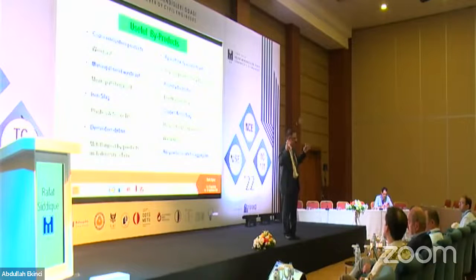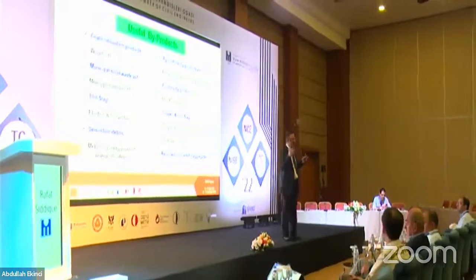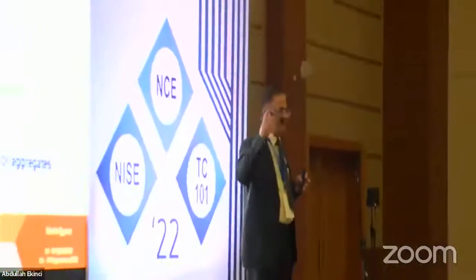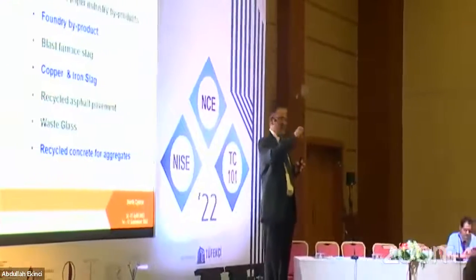Maybe all of you are aware of the research, but I want to give you some idea about what I'm going to talk about. Say you made a control concrete or the reference concrete, say 50 megapascal, for example. Then we made certain replacement, foundry sand, coal bottom ash, etc., and the value of the compressive strength has come down to say 25 megapascal. We as civil engineers, I do not know the mindset of the people in North Cyprus, but generally, compressive strength is one of the most important properties by which we define the concrete. So people say the strength has decreased by 30%, 40% or increased by this much percentage. So we always talk in terms of percentage.